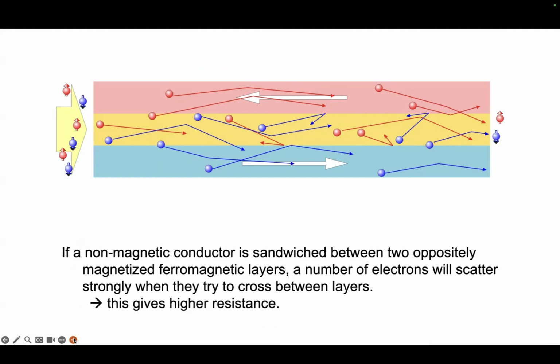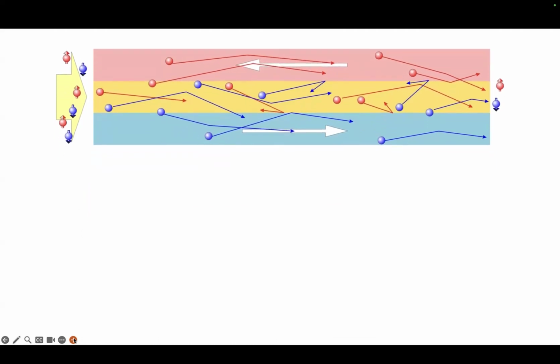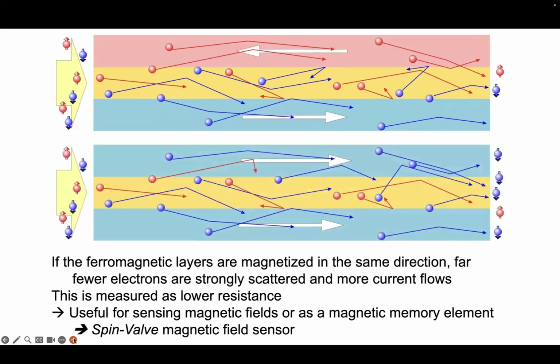Now the idea is that if we then switch the magnetic moment of these two ultra-thin magnetic layers, so they're parallel, now the blue electrons will be less scattered everywhere, and essentially the conductivity of this sandwich will be increased. So the idea is we can change the resistance of this sandwich if the layers are thin enough by simply changing the orientation of these magnetic layers. This is what we call a spin valve.